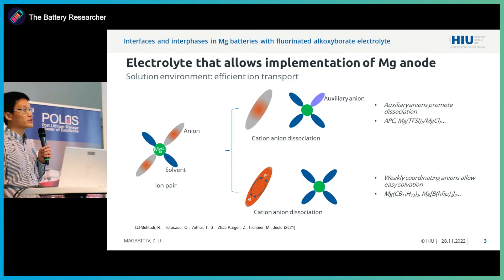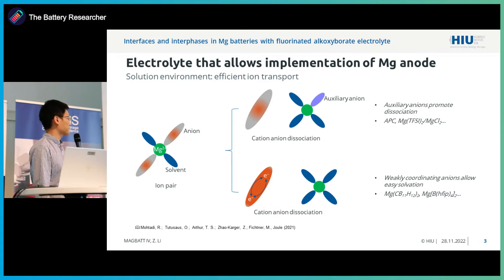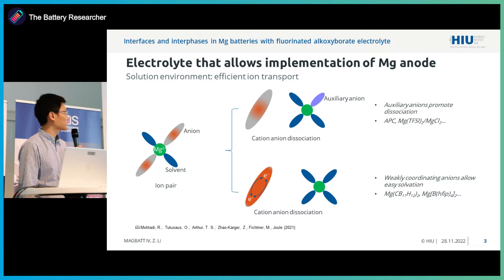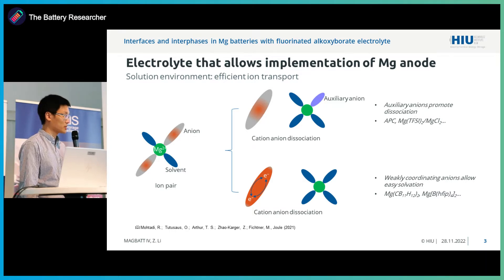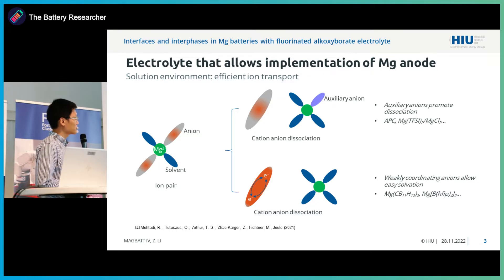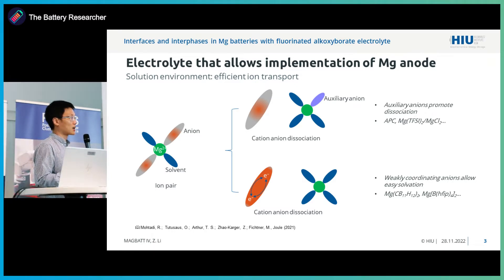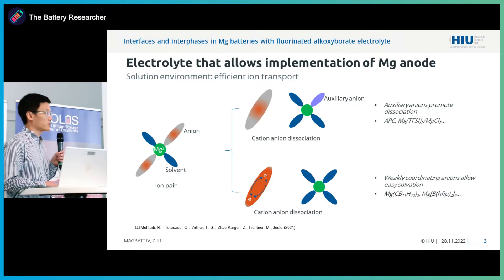This situation changed when chloride-based electrolytes were developed, as already mentioned by Darwin. There are a couple of chloride-based electrolytes — for example, the APC electrolyte and also some magnesium compounds with the addition of either magnesium chloride or aluminum chloride. With this chloride species, we are able to have better cation-anion dissociation. However, we should realize that here we are dealing with a corrosive environment, requiring a large amount of chloride species, which leads to corrosion issues.